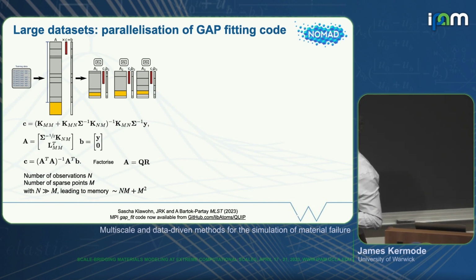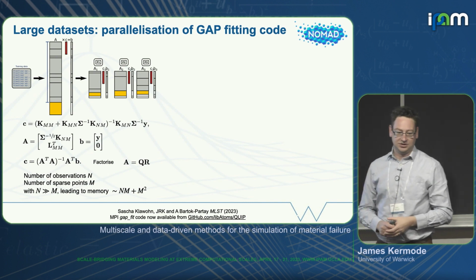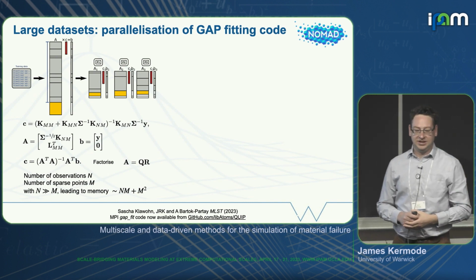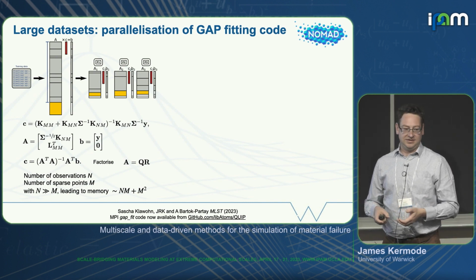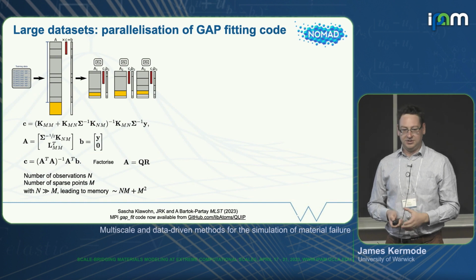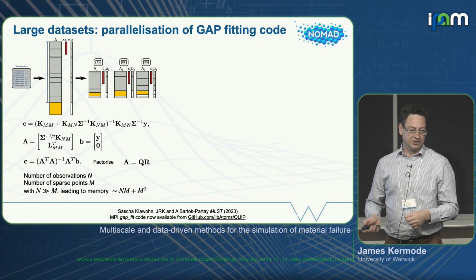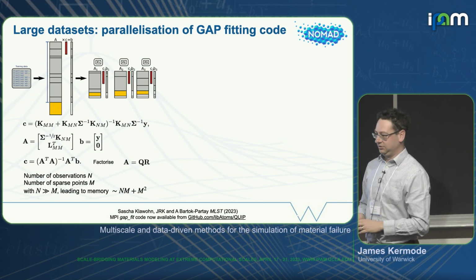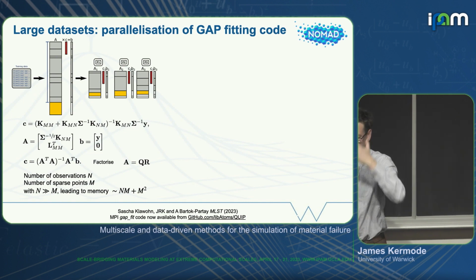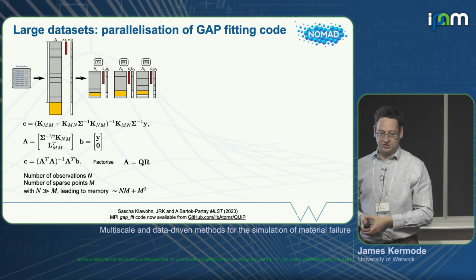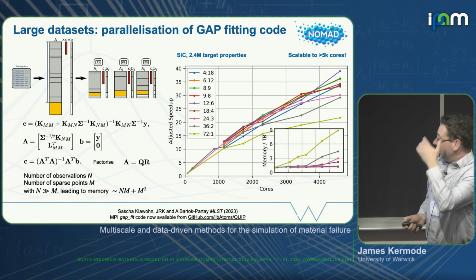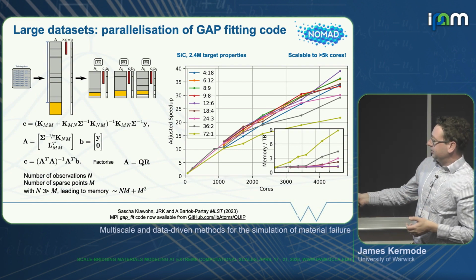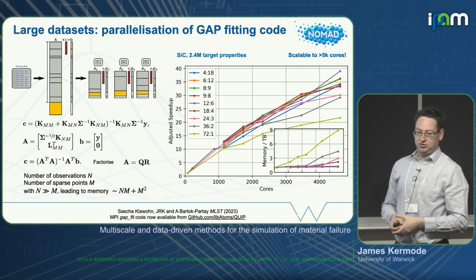And the challenge is that this matrix A is very, very large if you've got a lot of observations. And that was limiting the scalability of the approach to very large training databases. You needed to have enough memory to store this matrix and then enough time to be able to do the solve. And people were using multi-terabyte compute nodes in order to do that. What we've done is take that big matrix and split it up into pieces so that you can do this solve in a distributed way.